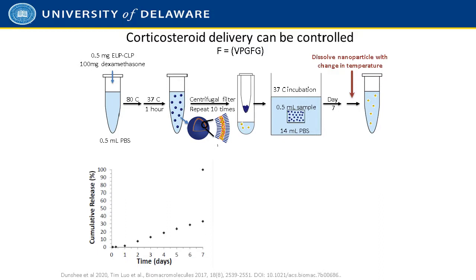Yeah, certainly. Thanks, Alvaro. So we can load hydrophobic compounds into this bilayer shown here. I hope you can see it, these little yellow nanoparticles. We can then spin down the vesicles to get rid of any drug or fluorescent compound that's not retained in the vesicles. Then as we move across the schematic on the right, we place the nanoparticles, they're perfectly redispersible, into small compartments in solution that are separated from the bath of the solution with a dialysis membrane. And then we can monitor the release of these small molecule drugs over time. If you look at the bottom right, we've done experiments over 3-4 weeks, but I show a 1-week time scale.